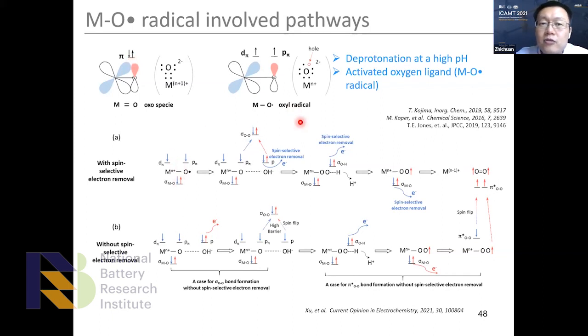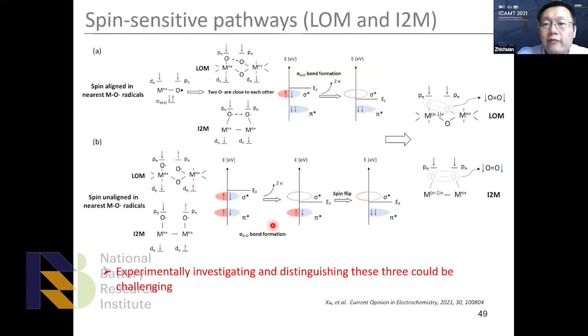So in this way, if we start from the radical, we can estimate, or let's say predict, the spin selected electron removal during the 4 steps of OER if we follow the AEM mechanism, such kind of reaction pathway. Or if we look at the LOM or the I2M mechanism, this will be even easier because the neighboring radicals can directly form the triplet oxygen bonds. So that will give a much lower kinetic barrier. So we now actually suspect this is pretty much the dominant reaction pathway for this observed reaction phenomena.